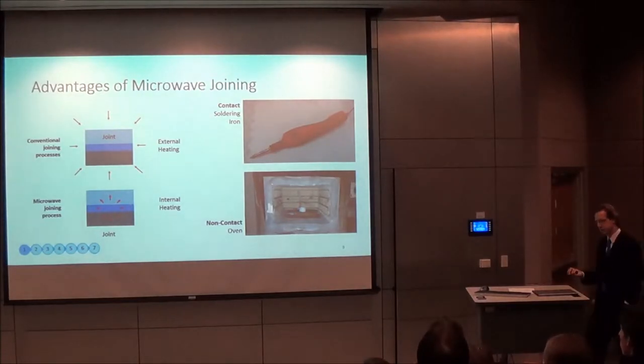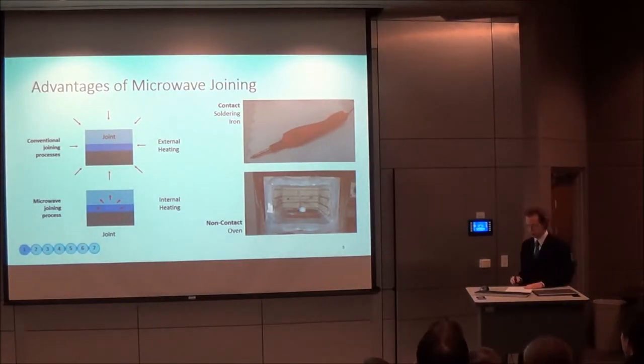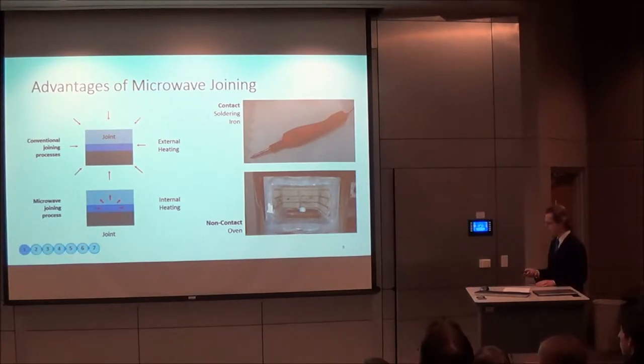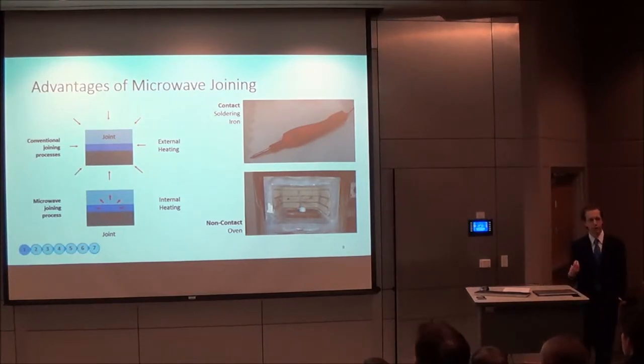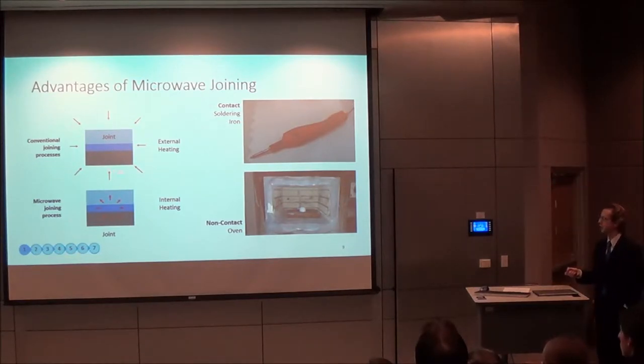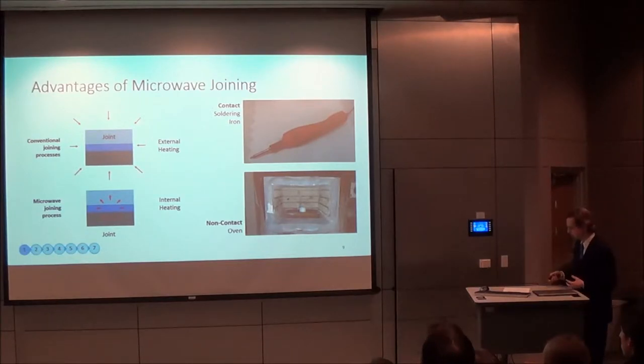There are some advantages to using microwave heating for joining processes, and the most significant one is that microwave energy produces heat directly in the material. So take an arbitrary joint where you have the base materials and the interlayer. Microwave heating can be used to apply heat directly at the interlayer, or at least internal to the base materials themselves, whereas conventional processes, either contact like a soldering iron or non-contact, transfer heat to the joint from the outside. And so you have this inside out versus outside in effect.